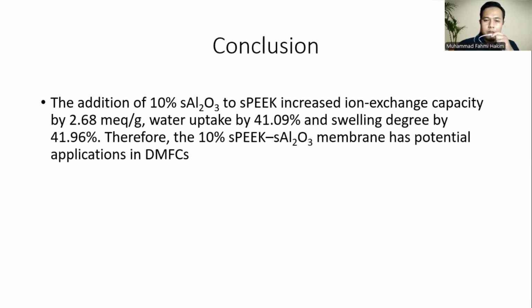Okay, from all of the characterization, we can make a conclusion. The addition of 10% aluminum oxide to sPEEK increased ion exchange capacity by 2.68 milliequivalent per gram, water uptake by 41.09%, and swelling degree by 41.96%. Therefore, the 10% sPEEK aluminum oxide membrane has potential application in direct methanol fuel cell.